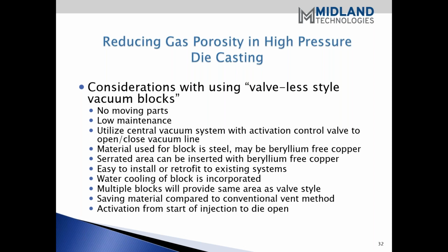You can also have a copper insert that would go into an H13 holder block. And so if you're more comfortable with using copper for your vent blocks, you can use one that has a steel holder block, and you can replace the copper inserts during your PM. They're easy to install and retrofit to existing systems. So if you have a valve block in your die now, you can easily replace that with a valveless vacuum block, depending on the situation, but it's easily retrofitted.